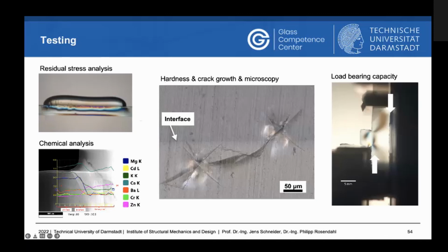And this result is actually really promising, and basically you only see how we broke glass, but it shows that this crack, for instance, traveled across the interface, and this one too, and not along the interface, which means that we have a very good connection between the added structure and the base plate.